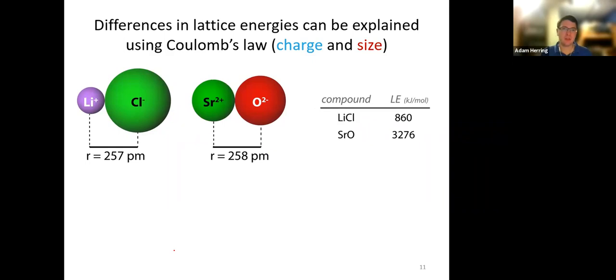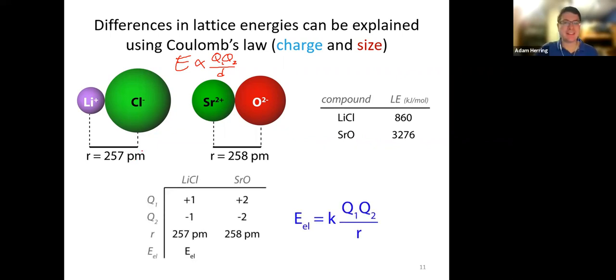So let's take a look first at differences in lattice energy based on the charge of the species involved. The lattice energy of lithium chloride is about 860 kilojoules per mole. Strontium oxide is about 4 times that much. Now, Coulomb's law says that the energy of the attraction is directly proportional to the product of the charges over the distance between them. We note that the radii between the nuclei is almost identical. It's only 1 picometer difference out of 250 or so picometers. So it's a very, very small difference, and we can attribute the difference in the lattice energy solely to the difference in the ionic charges.